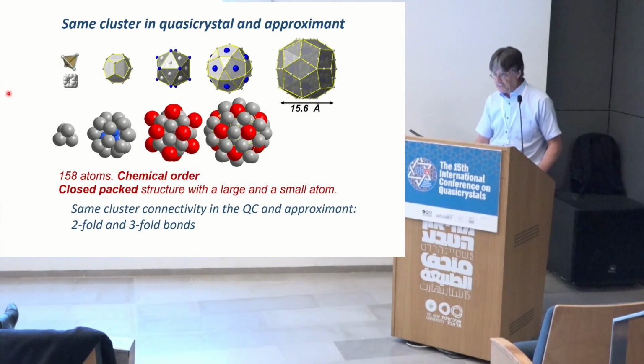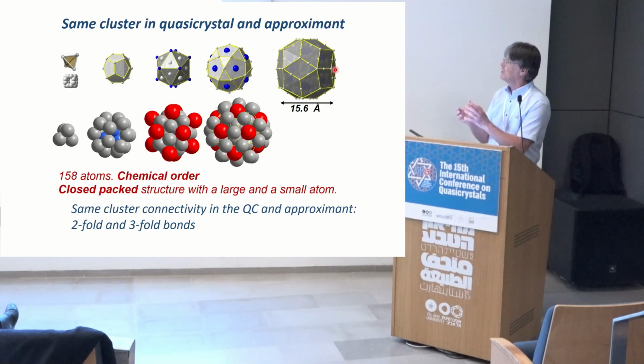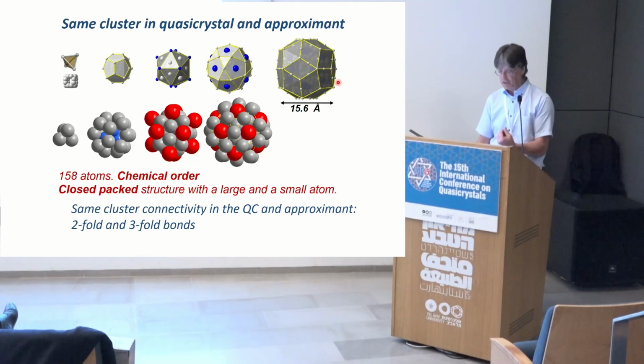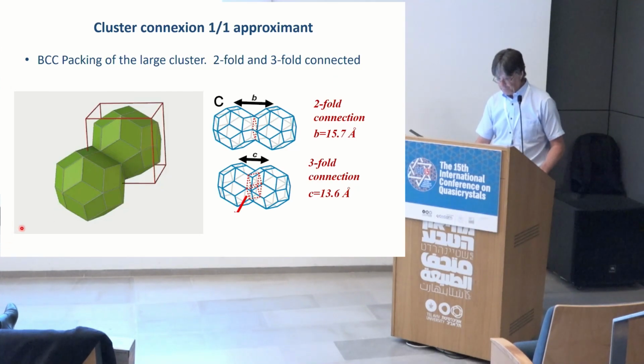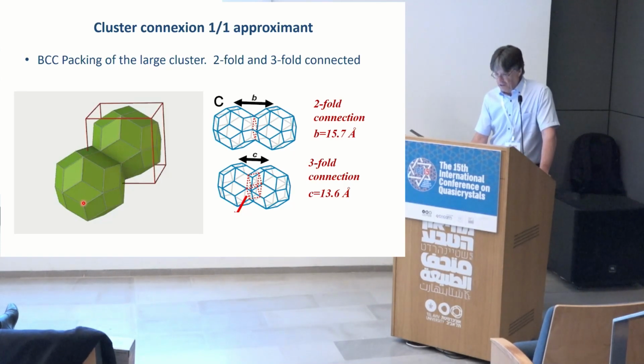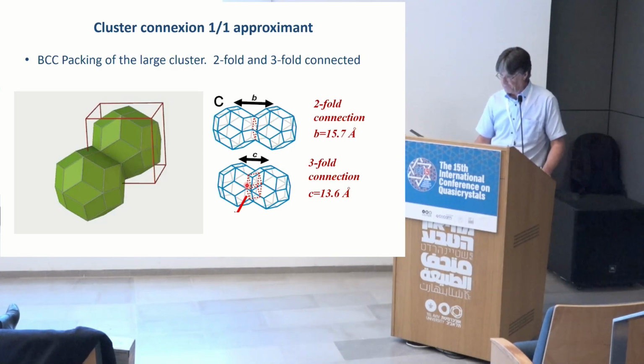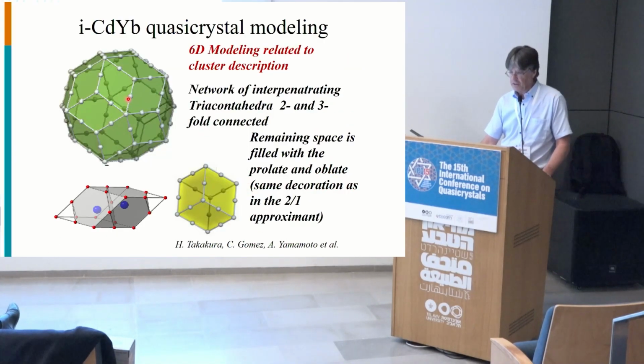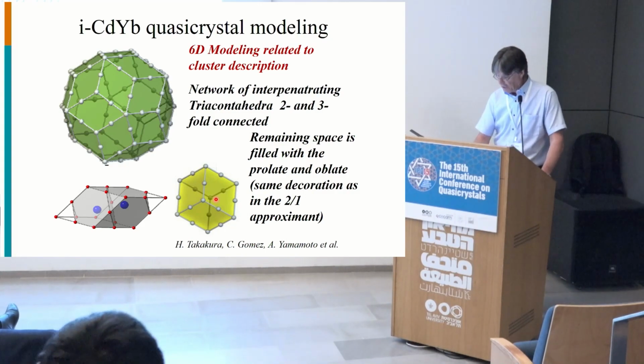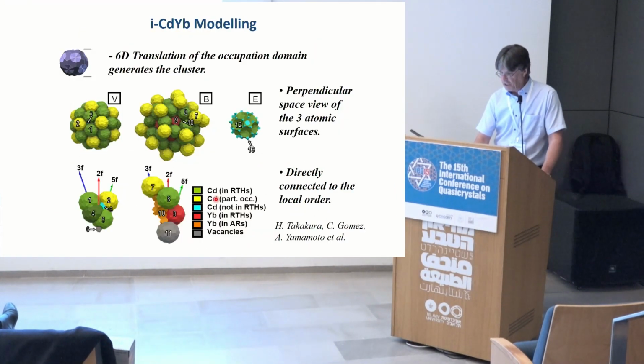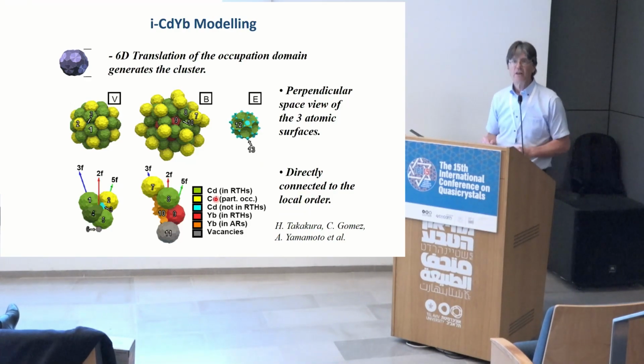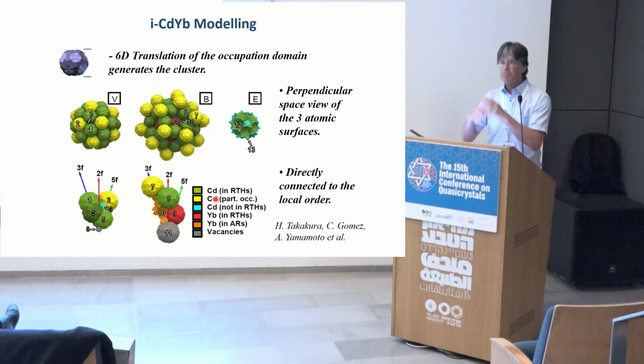But the main point is that in the 1-1 approximant, we could know how this is connected, what the structure is, and we can use this information to derive the connection in the quasicrystal. In the 1-1 approximant, it's a BCC stacking, and there is an overlapping structure shown here. It's connected along twofold, and it's overlapping along threefold. And using these building blocks, and using the knowledge we have from the diffraction pattern, which I will skip here, we can derive a complicated six-dimensional model. And that's because we had all those tools.